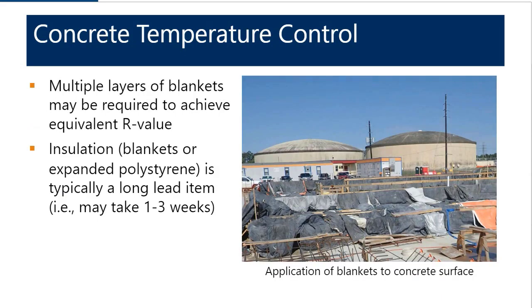And so after the concrete is placed and the temperatures are being measured, you'll want to apply blankets to the concrete surface. And so for a lot of folks, this is somewhat counterintuitive because the thought process is, don't we want to get the concrete to cool down? Why are we putting blankets on it to keep it warm? And so one of the things that we also remember is that we're concerned about the temperature difference between the core of the concrete element and the surface, and we're trying to minimize those differences to mitigate thermal cracking. And so blankets are put on the surface of the concrete to help mitigate thermal cracking due to large temperature differences. And so here on the right-hand side, you can see multiple layers of insulated blankets that have been applied to a large foundation element.